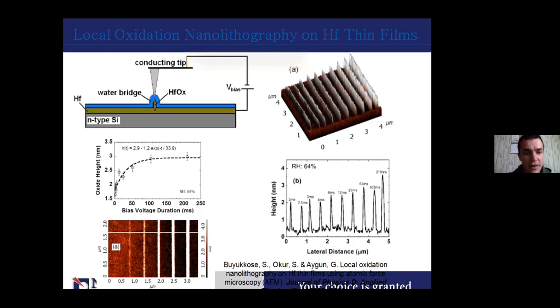size of the oxide layer on the surface. So you can see on the bottom the two-dimensional image of the results, depending on how long we stay at which point. You can see that we have different sizes of the oxide layer on the surface. And also on the right, you can see the 3D image of the same area, and you can see how it looks. We have the height of these lines of about a few nanometers, from 1 nanometer to 4 nanometers. And the 4 nanometers is the right line, when we apply the voltage for a much longer time. So you can see how we modify the surface, and it's not a charging of the surface. It's really that we grow the oxide layer on the surface, which remains forever on this surface. So in such a way, you can do some modification and maybe create some nano objects on the structure of the thin films.